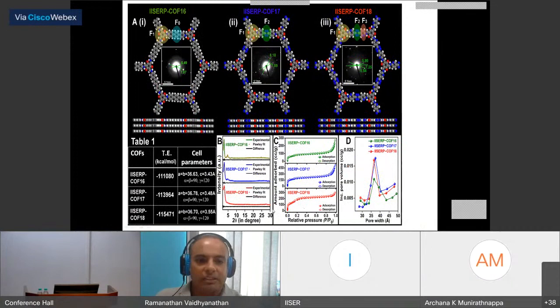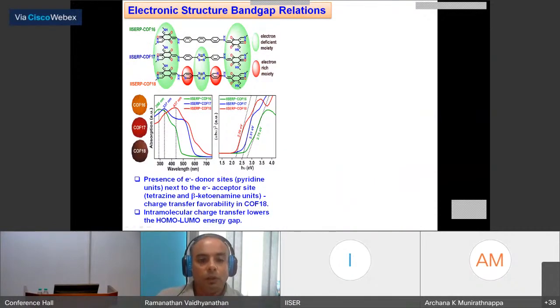And the structure is very crystalline. You can see the SAED pattern giving diffraction, which is fantastic. And it is also seen in the PXRD, porosities are kind of similar for all of these because the linkers are of the same size. So that is possible. And as I told you, you have electron deficient centers shown in green, you have electron rich centers shown in red, and there is a push-pull concept, and that has been systematically introduced into the COF's polymeric framework. And then from UV visible spectroscopy, using Tauc plots, we calculate the HOMO-LUMO gap,